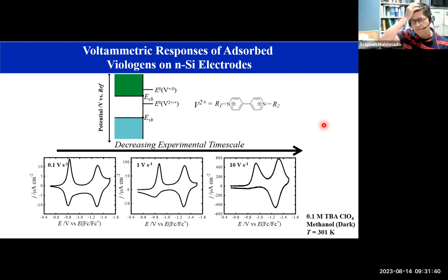So these are all voltammetry plots at different scan rates as indicated in each of these panels. Now, the interesting thing right off the bat is that the shape, particularly of that first redox wave, is highly dependent on the scan rate. The second redox wave is not really dependent on the scan rate beyond the amount of IR distortion that happens when you start passing a lot of current at large scan rates. The redox event on the right side in each of these plots looks like what a molecule gives on a metal electrode if you stick it on its surface. But this first redox wave, that doesn't.